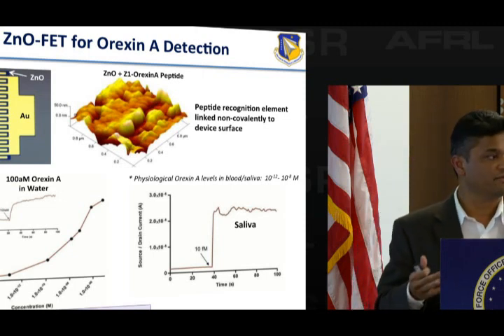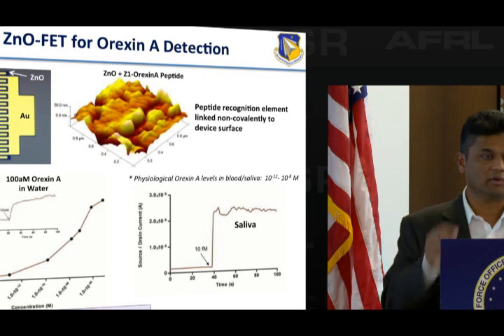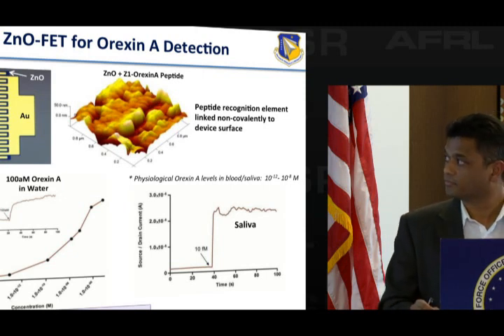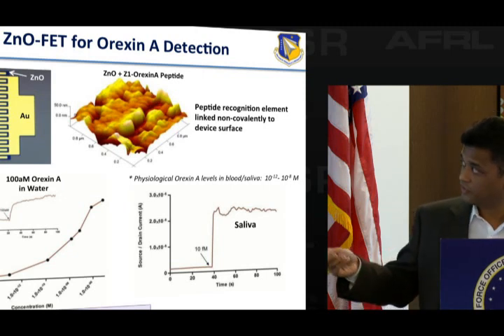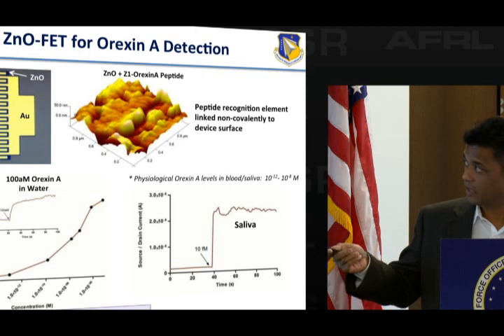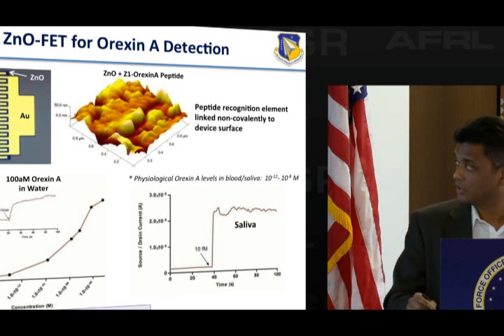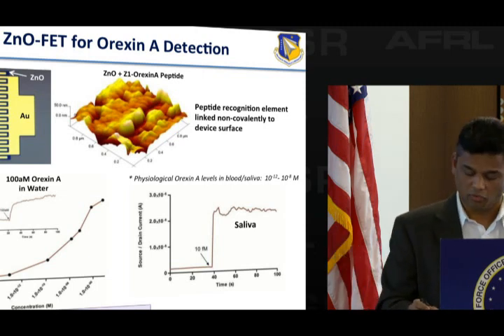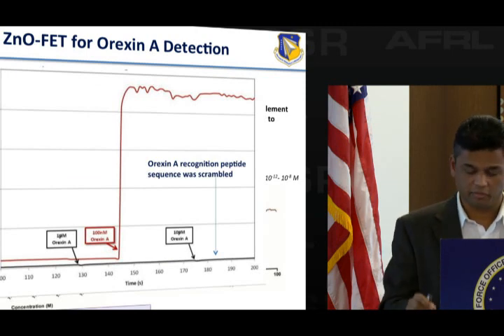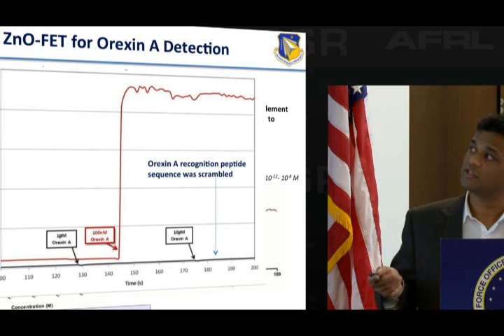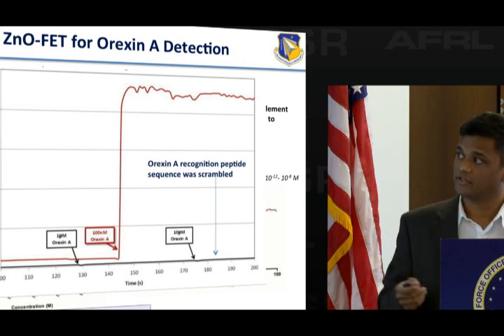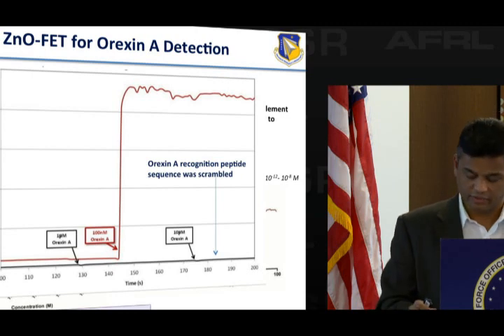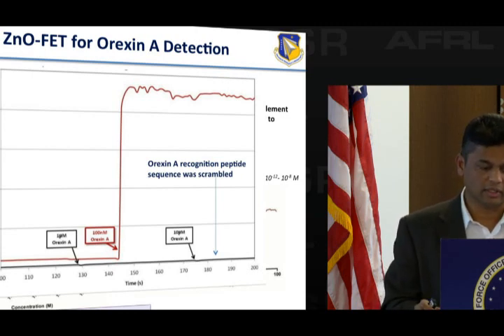And you know, saliva is a nasty medium because there are other interfering molecules, so we just spike it with a little bit of orexin A and you can detect it. And I just put here physiological levels of orexin A in the blood are anywhere between 10 to the minus 8 and 10 to the minus 12 molar concentration. So you have to be sensitive enough to be able to detect that. So what we've achieved is providing onto this device molecular recognition properties that can be used to sense specific markers in the saliva.